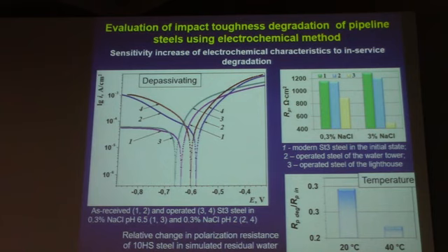It should also be noted that there are only a few estimations for application of this method for evaluation of degradation degree of steels, and for more well-grounded conclusions, it would be useful to carry out additional investigations concerning first of all selection of electrolyte for electrochemical tests, which should not necessarily be the same as the operational one, but should provide a maximum sensitivity of electrochemical characteristics to material degradation. And presented here data show that sensitivity of electrochemical properties can be increased by applying depassivating solutions or by increasing test temperature. Also, it would be a very perspective study concerning obtaining similar correlation dependence for other mechanical properties, whose prediction might be more useful in engineering calculations, for example, fracture toughness.